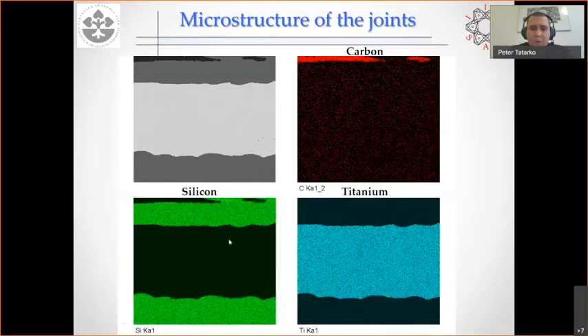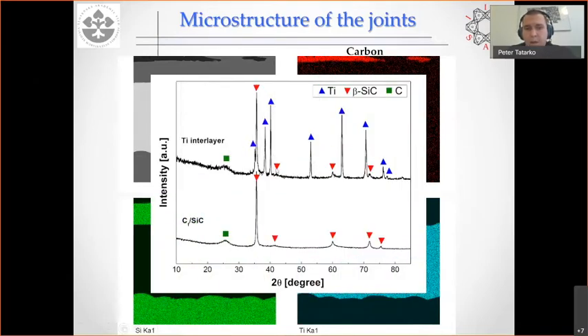We wanted to see what is the chemical composition of the joint, but you can see clearly there is only titanium. You don't see any silicon or carbon diffused into the layer. Truth be told, we also did EDX by TEM, because this is on SEM. We found a very little concentration of silicon and carbon in the titanium, but basically the concentration of these two elements was not enough to produce phases, as will happen later, which I will show you. This was also confirmed by XRD results. You see only titanium, these blue triangles, only titanium we found.